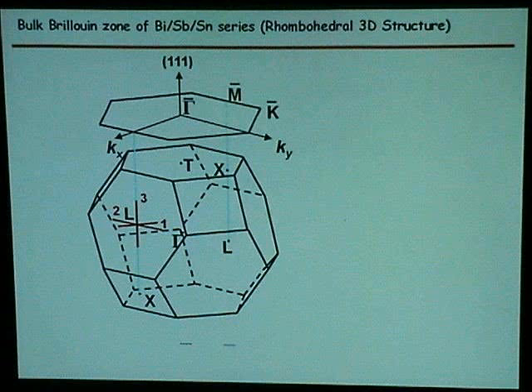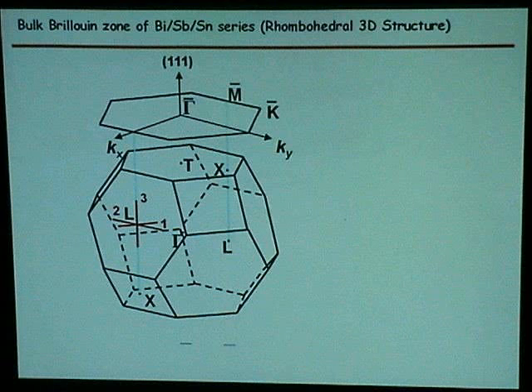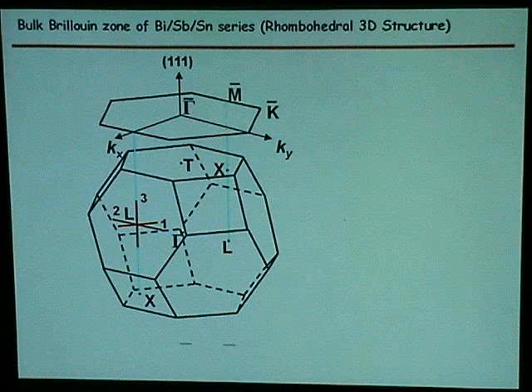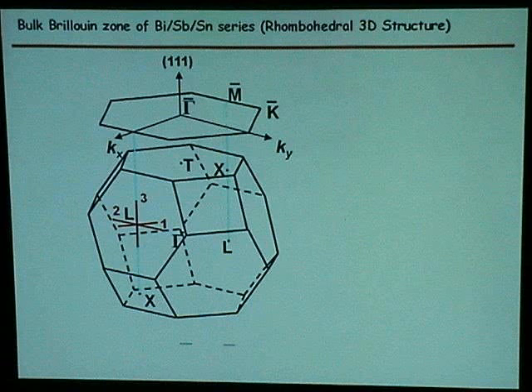But there is a challenge here. The challenge is that this bismuth will not cleave in all surfaces. The best cleave you can get is on the 111 surface, and if you're lucky, you can get a cleave on the 110 surface. Other than that, it's not easy to cleave. So we decided to explore the 111 surface in some detail.